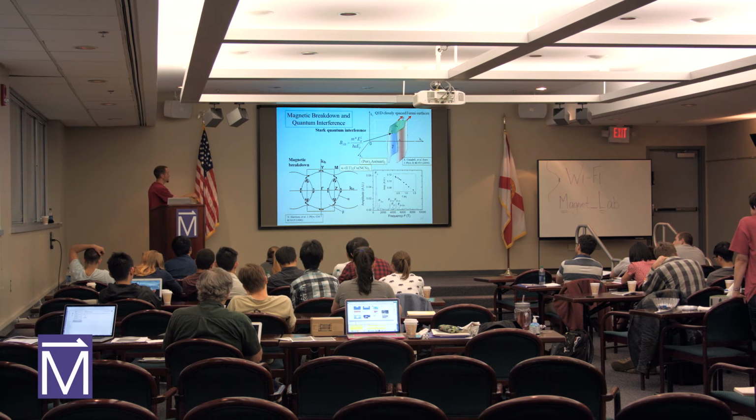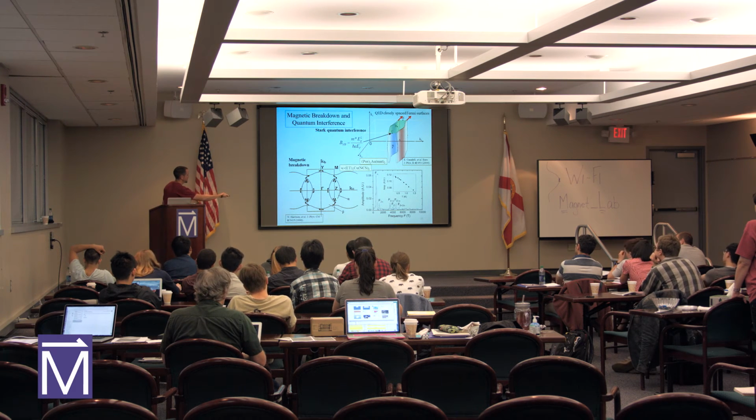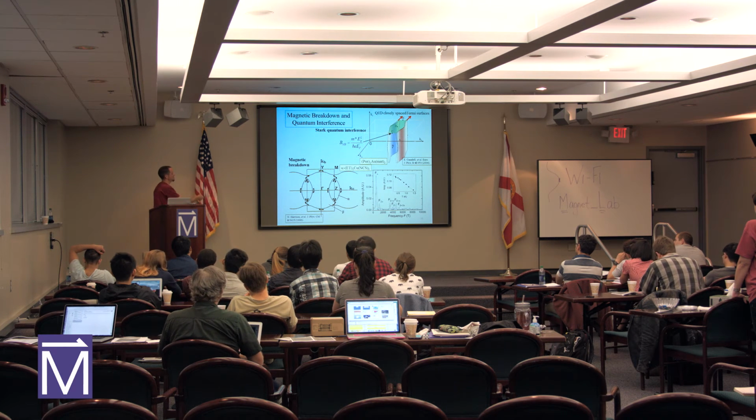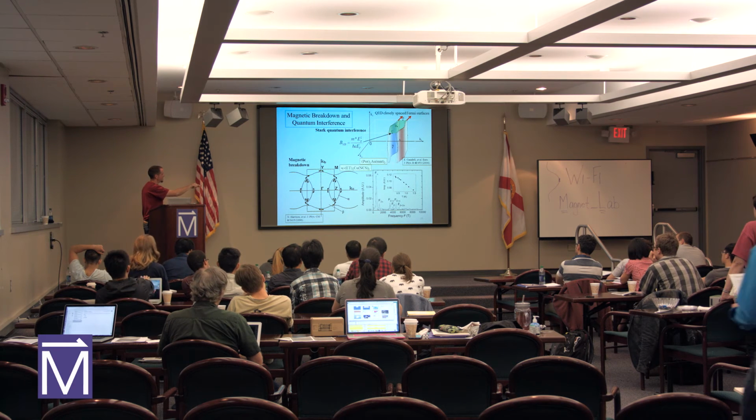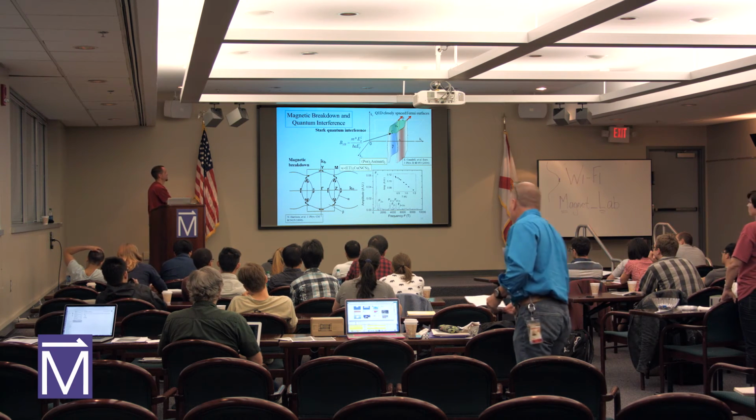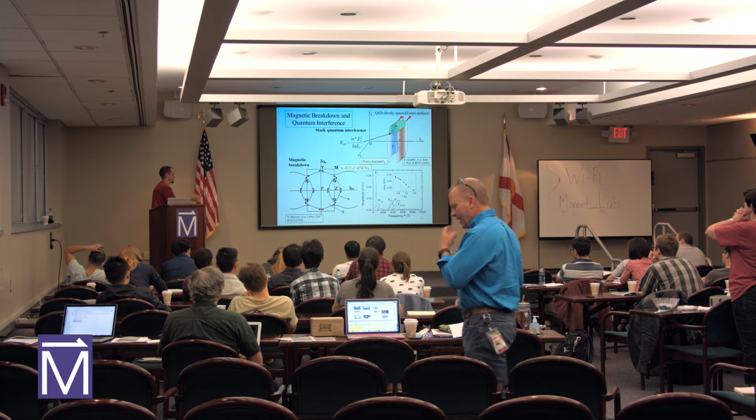When you have magnetic breakdown, you can also have very strange effects. It doesn't have to go in this large circular orbit. It can also go in an orbit and skip to the inside of this pathway. So if you take a full set of data with the magnetic field for this sample, you'll actually get a fast Fourier transform spectrum that shows all the different strange shapes that this can take. The carriers can go along these closed orbits, the bigger orbits, and also any combination in between. So quantum interference and magnetic breakdown.